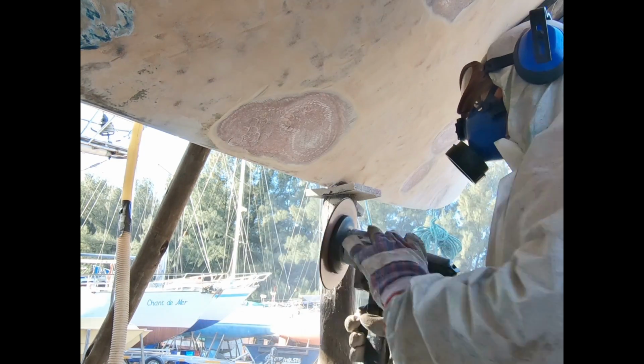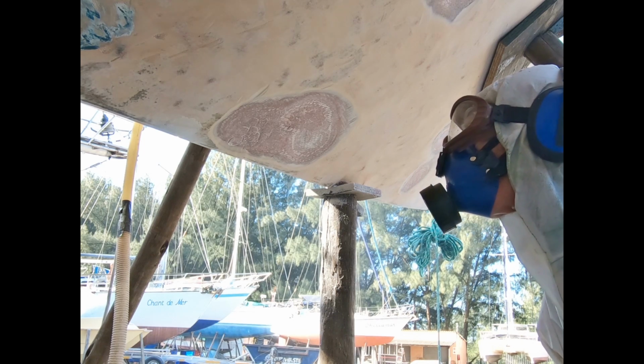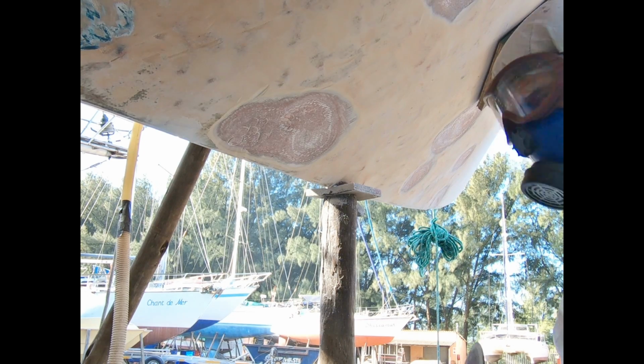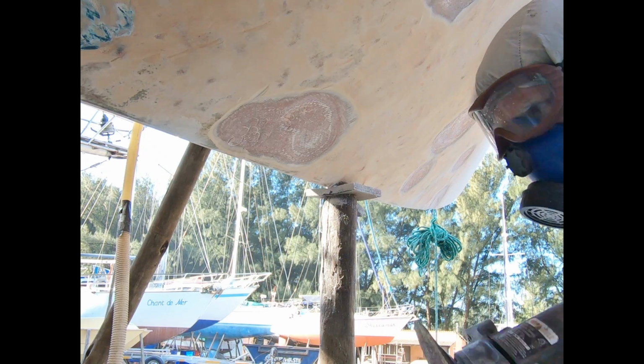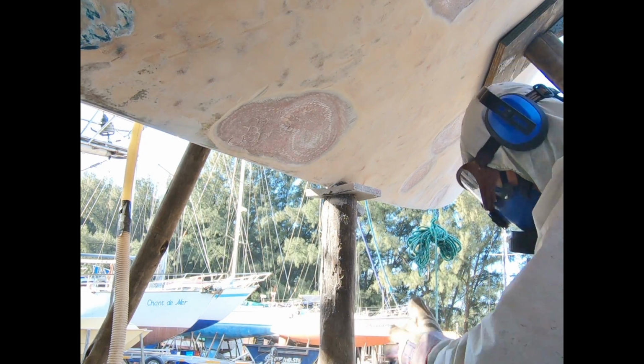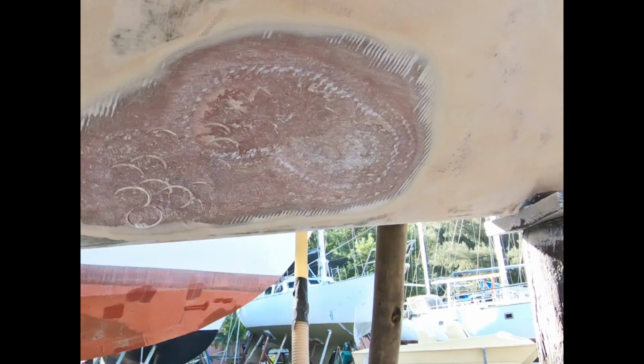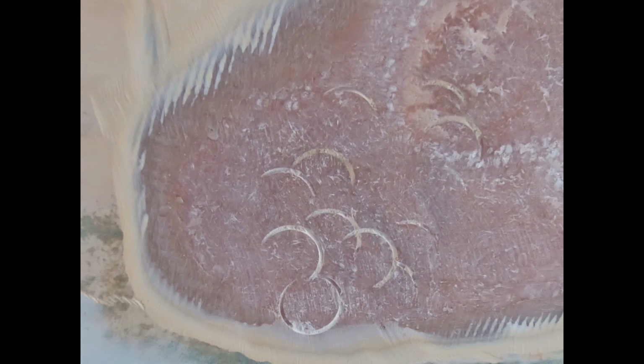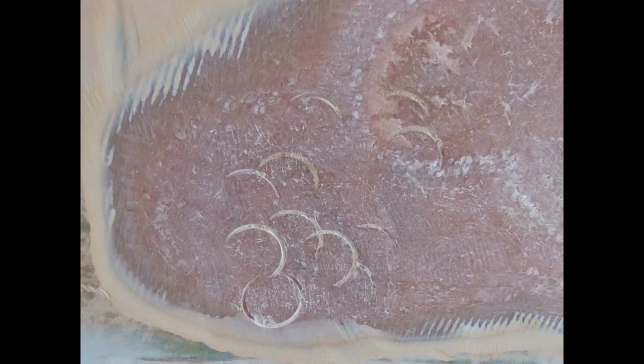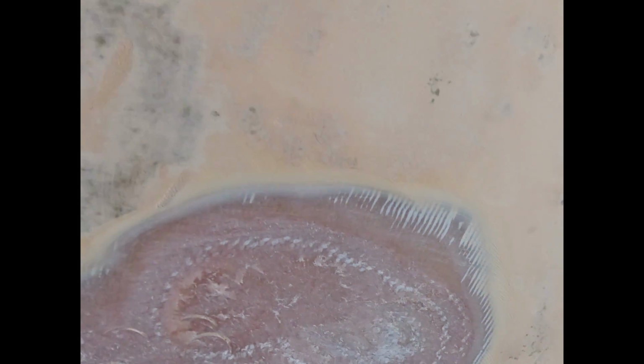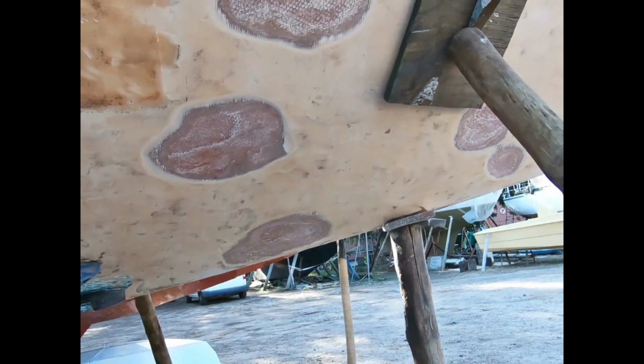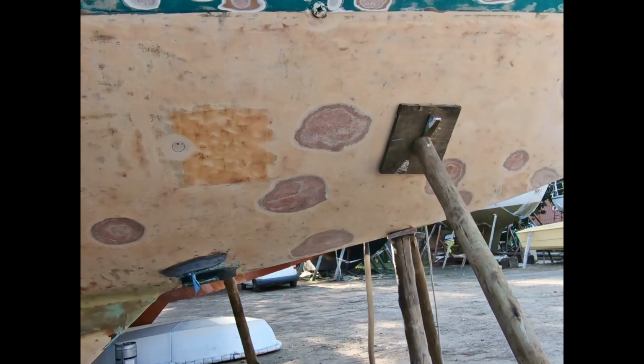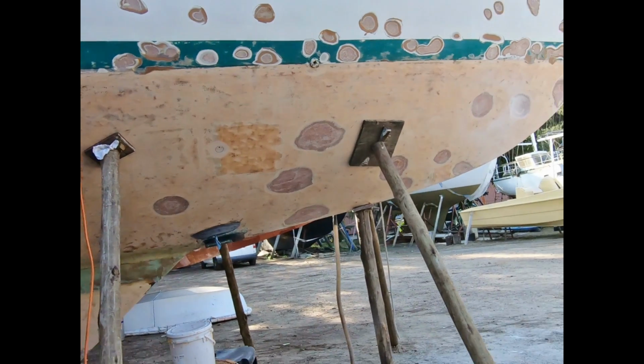So what starts out as a shallow blister can wander off in any direction and then become a deep pit going through many layers of fiberglass. Those vertical parallel stripes are where this boat was peeled below the waterline only in 2001 and treated for blisters at that time. It is quite obvious that just surface peeling to a particular depth is not the best way to go, because these blisters originate at all different depths within the laminate layup.